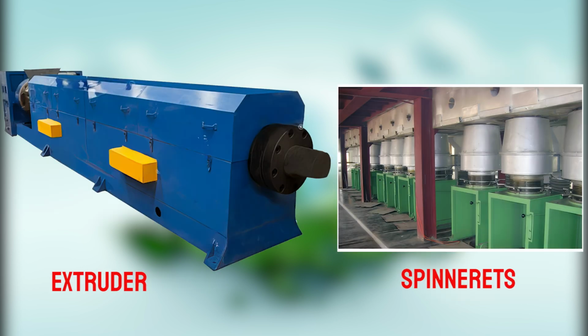Extrusion. The PET flakes are melted in an extruder having 6 heating zones. From the extruder, the melt goes through a continuous polymer filter to the 2 beams. The melt flows out from the spinnerets in the form of continuous filaments and is cooled by quenching air, the temperature of which is maintained at about 18 degrees C. The filaments of all positions collectively form a tow in the take-up unit. In take-up, spin finish is applied to the filaments in all positions individually.